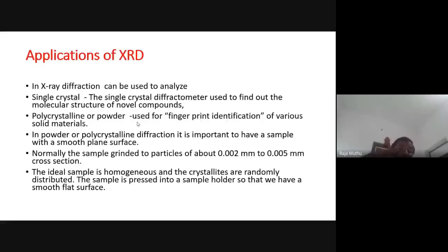In powder or polycrystalline diffraction, it is important to have a sample with a smooth, plane surface. Initially, it has to be ground, and the particle size is supposed to be 0.002 mm to 0.005 mm in cross section. It has to be ground with the help of mechanical milling. The ideal sample should be a homogeneous mixture, and the crystallites are randomly distributed. The sample is pressed into a sample holder so that we have a smooth flat surface.